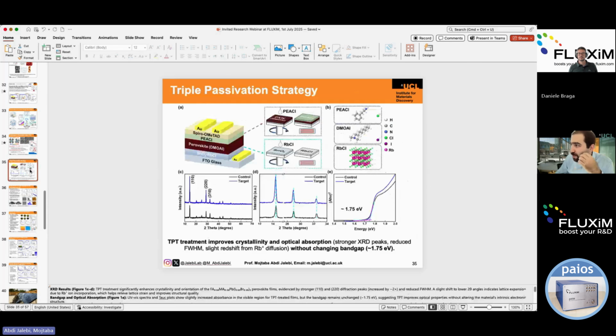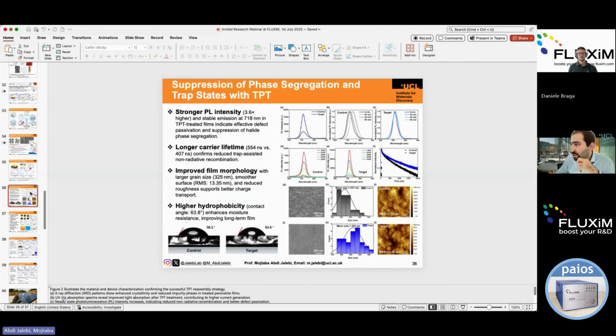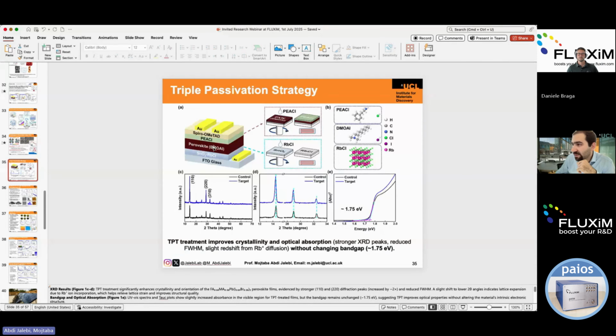The other passivation molecule we are using is DMAI. This is the passivation molecule, as you can see over here, a small molecule, so we are using it inside the perovskite precursor. It has been shown to have a great impact on the wide bandgap perovskite, specifically designed for that. It helps us to prevent the ion migration, by passivating the defects at the interfaces, especially at the grain boundaries, and also providing excess halide into the system.